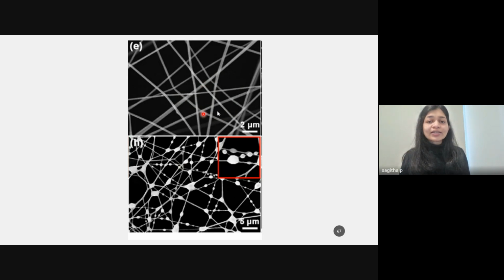So this is the simple polymer without filler, and this is the SEM image of the polymer with the filler graphene oxide. So this image shows that the polyacrylonitrile itself is not able to provide any air filtration efficiency, or it is not able to trap particulate matter in its structure. But what we can see is that when graphene oxide is incorporated, the particulate matter is getting adsorbed or trapped inside the nanofiber layers.